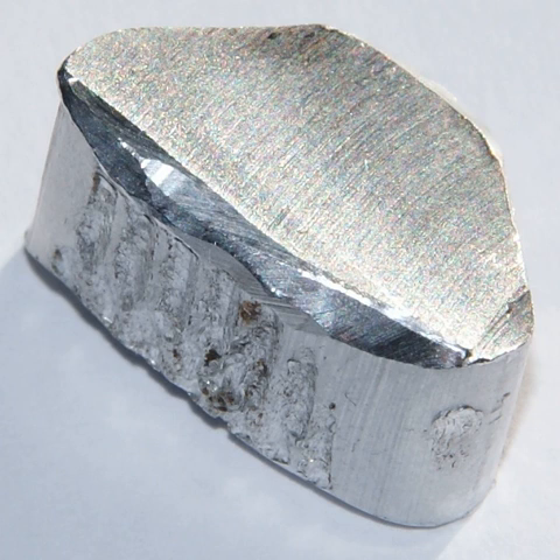Despite carbon's resistivity against corrosion, it is still consumed at a rate of 0.4 to 0.5 kg per each kilogram of produced aluminium. Cathodes are made of anthracite. High purity for them is not required because impurities leach only very slowly. Cathode is consumed at a rate of 0.02 to 0.04 kg per each kilogram of produced aluminium. A cell is usually terminated after 2 to 6 years following a failure of the cathode.